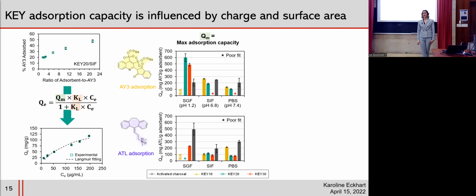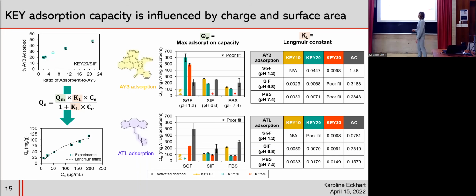We next sought to understand why these results were happening. So we look at the KL value for this. The KL value is the Langmuir constant, and this can be related to the surface area of the adsorbent and the porosity, implying that a higher surface area and higher porosity results in a higher KL value, which enables higher QM value or higher maximal loading. And we see here that the KL values for activated charcoal are 2 to 3 orders of magnitude larger than the keys. And this result suggests that activated charcoal has a much higher surface area compared to the keys, and that's what's really driving its successful adsorption.